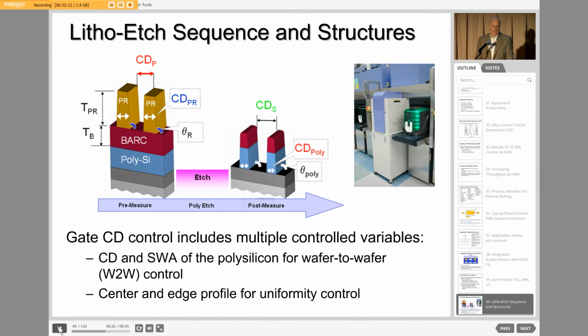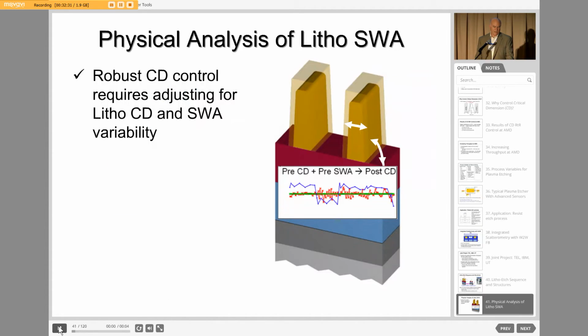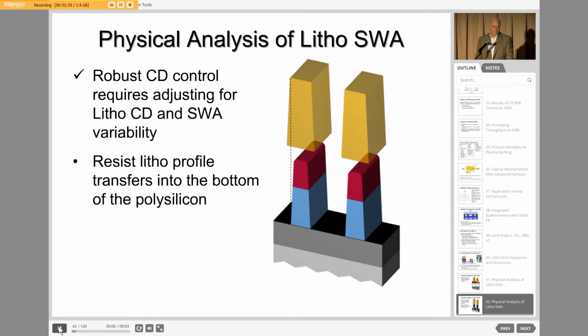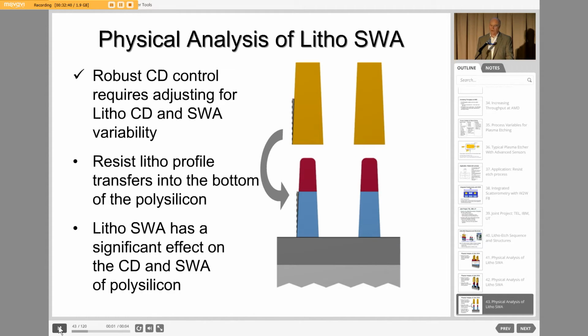So again, adding the sidewall angle, which was found to have a significant effect on the performance of the chip, was essentially a new part of this. And of course, the other problem is how do we model the system? We have to understand what the interactions are between the different variables. Here again, you see how the profile is going to transfer onto this polysilicon. And then we're going to try to understand exactly how all the different variables are related.